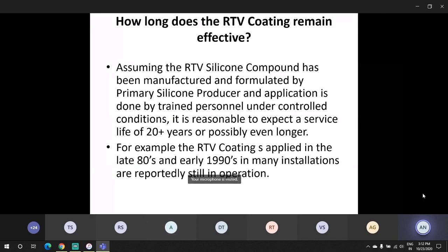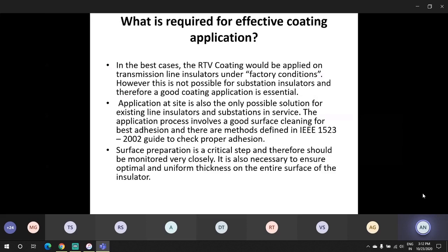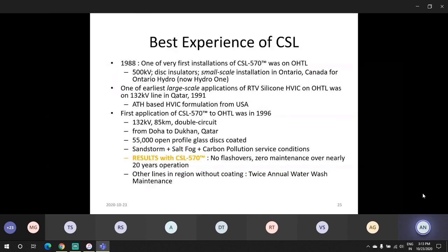We can confidently say the service life of the coating will be 20 plus years. In India, our oldest coating is now in service for more than 16 years. And outside India, our coatings which were done in the 1990s are still in operation. The effective coating application has to be in accordance with the application manual or the guidance issued by the manufacturer and the methods defined in IEEE 1523. In our case, our oldest application was done in 1996, a 132 kV, 85 kilometer double circuit line. This is still in service even after more than 20 years.